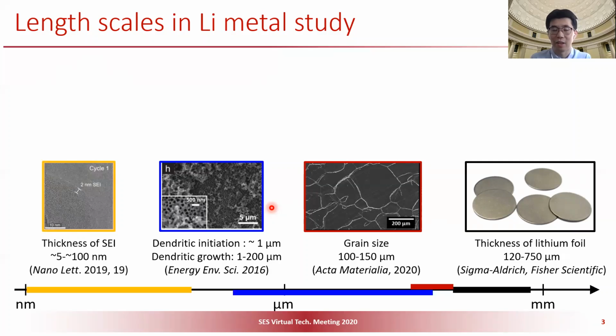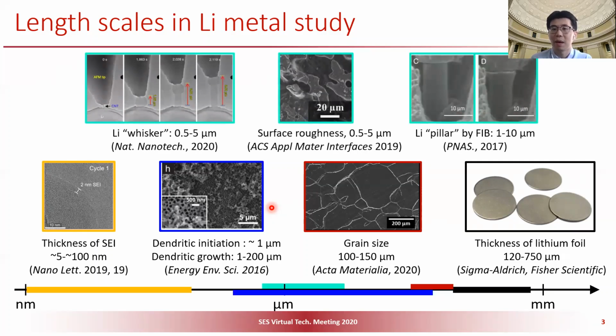And as many of us know, on the anode side, on the surface, there is always a thin layer of a so-called SEI film. So this SEI film is about 5 to 100 nanometers. Also, in many publications, many people study different phases of lithium. For example, this is a whisker. A whisker is usually about 0.5 to 5 microns. And many people also study the surface roughness of lithium foil. It's about 0.5 to 5 microns. And also, many people use focused ion beam to cut a pillar of lithium. Such a pillar usually has 1 to 10 microns in diameter and also in height. So this picture gives you roughly an idea how many length scales there are.